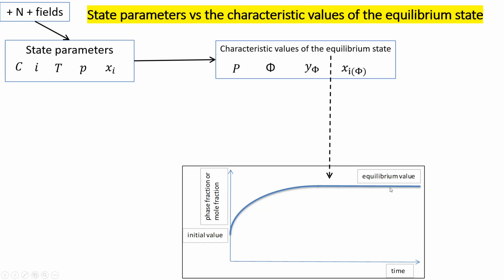But to tell the truth, it's a true equilibrium only if you try a second experiment under the same state parameters, when you create the initial state different, with a larger value than the equilibrium value, and it comes to the same equilibrium value from the top, not only from the bottom. Then you can call it the equilibrium value. Of course, you can ask me how you can start lower or higher than the equilibrium state.